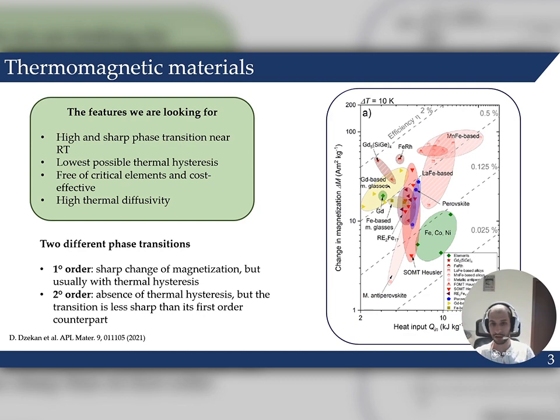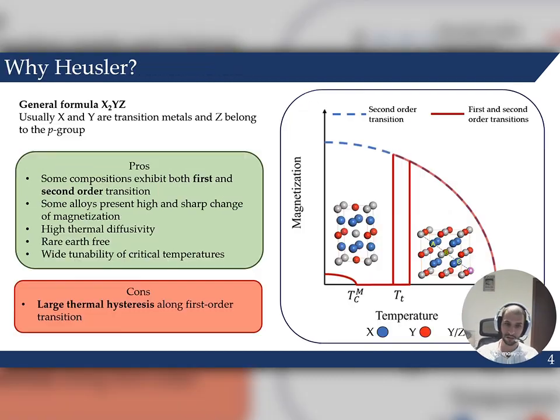And in my work I'm focusing on Heusler compounds. Heusler compounds in fact are a very large material family with the general formula X2YZ, where the first two elements generally belong to the d group, while the Z elements belong to the p group. One of their most interesting features is the fact that some compounds exhibit both a second-order Curie transition and a first-order magnetostructural transition, the well-known martensitic transition, that is characterized by a very high and sharp difference in magnetization. Furthermore, Heuslers generally exhibit good thermal properties, and they are also rare-earth free.